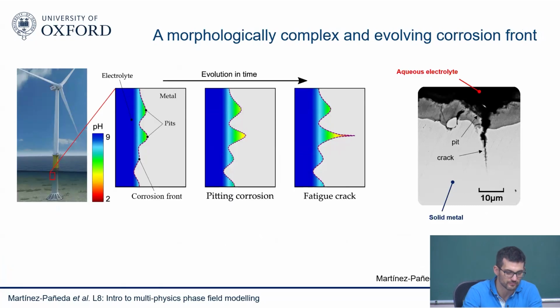As I told you yesterday, the main issue with the durability, or the service life, of offshore wind turbines is corrosion fatigue. This is the limiting factor. And what happens typically is that you generate some pits at the interface between the electrolyte and the metal. They grow, basically driven by local chemistry and mechanics, and then eventually you get a pit to crack transition event, and then the propagation of fatigue cracks. You can see here a microscope image, solid metal, the aqueous electrolyte, how you start with a pit and then eventually it becomes a crack. And this is a challenge because you have a very complex corrosion front, and everything, as I said, is strongly coupled.